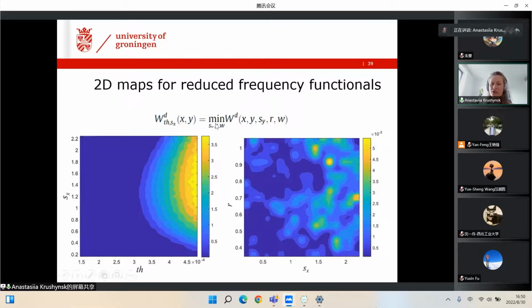And because these data show the minimum of the reduced frequency functional, the other parameters cannot be tuned to improve, let's say, to minimize the difference in frequencies. So that means that these values are not appropriate for our design if we want to deal with resonant type flight. On the other hand, another pair of parameters here shows a completely different response, because the values in the legend are very small. That means that almost every choice of these values will give us values very close to the resonant frequency. Yes, because the difference, so here you see in colors, is of the order of 1/10. So this is how to interpret them.